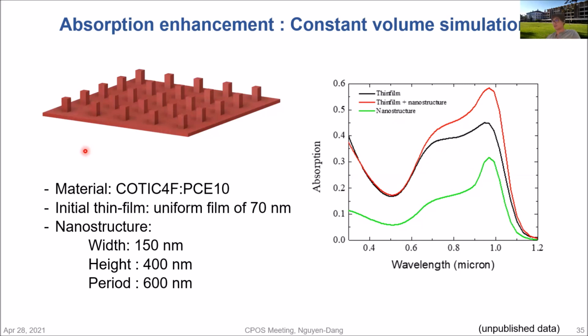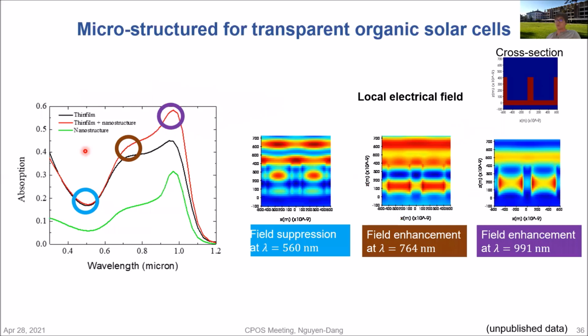And this peak, as you see on this green curve here, comes from the interaction between the different pillars inside the structure. If we zoom in and consider what the fields look like, you can really see that at the dip here, there is no field added by the nanostructure, whereas at the highest peak here, the field is extremely strong and localized inside the pillar. So this simulation is one of my motivations for working more on maybe making nanostructured organic solar cells.